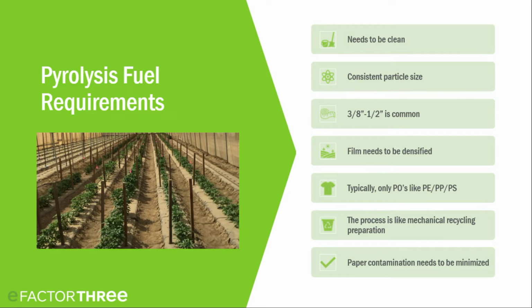So in our experience in the projects we are working on, we found out that it has to be fairly clean, with little dirt contamination. It has to have a consistent particle size. If it's rigid, it needs to be somewhere in the 3/8 to 1/2 inch particle size. If it's film, there's certain technology that can take the film flake at 1.5 pounds a cubic foot. Others have to densify it. Typically only the polyolefins, the PEs, the PPs, and the PSs.